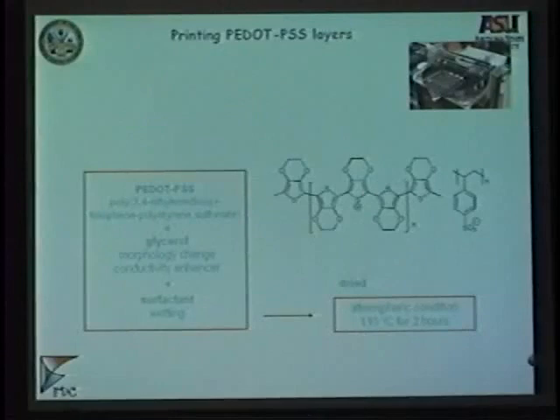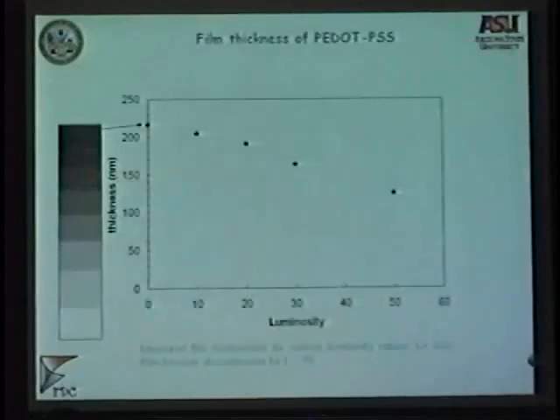Well, let me skip this because here it's similar. Every time we print, since we're trying to demonstrate the principle here, we're not making devices that the companies will use. We do everything in atmospheric conditions, and we bake the PEDOT-PSS, a conducting polymer. We bake it at 110 degrees C for 2 hours. You could see that we do include some surfactants to modify the chemistry, the wetting, and then the glycerol here is put in order to enhance the conductivity of this polymer, because it allows for some adjustments of these chains in certain areas and increases the conductivity.